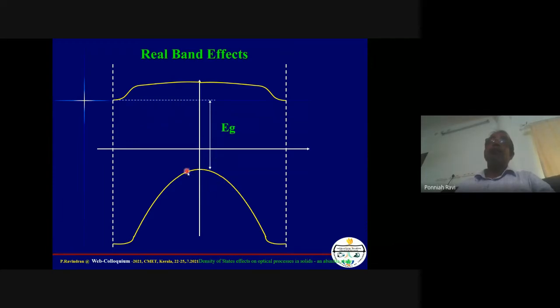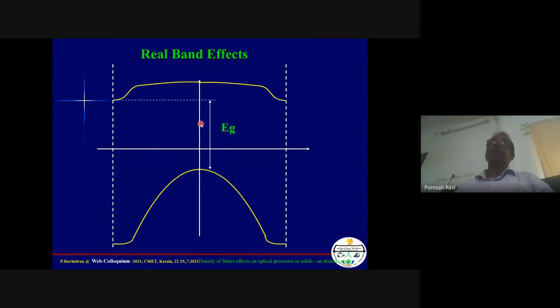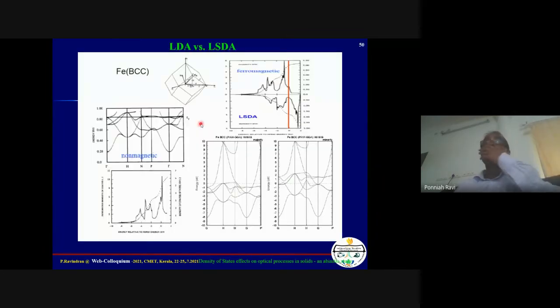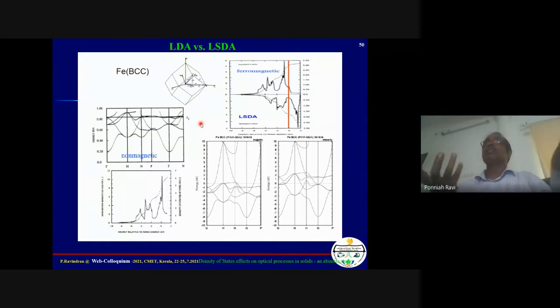Optical excitations follow selection rules: if both valence band maximum and conduction band minimum have the same character (S to S transitions), these are forbidden. Then optical absorption starts at higher energy where, for example, S to P transitions are allowed. This means the optical band gap may differ from the band gap obtained from the band structure. Also, when we have a non-magnetic material, the band structure and DOS are the same for both majority spin and minority spin electrons.